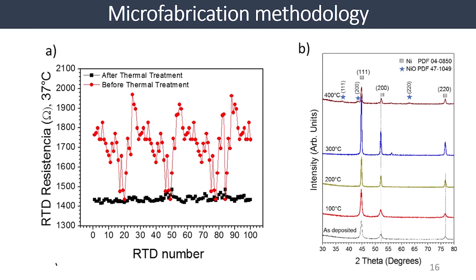This slide explains why the thermal treatment is important. In the first graph, we show each of the RTDs with its consecutive number and also the resistance value of each RTD. Also, it's important to mention that for each wafer, we have approximately 100 functional RTDs. With red dots, we represent the resistance of each of the RTDs along the wafer. We can see that there's a very wide difference between each of the RTDs before the thermal treatment. But after the thermal treatment, we see a very narrow difference, very homogeneous values in each of the RTDs. The reason is that the crystallites of nickel have bigger size, resulting in fewer grain boundaries.